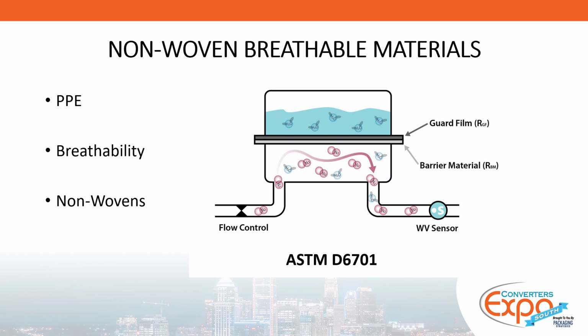And how can I be sure, conversely, that the other side is dry when so much moisture is moving into the dry environment? And this was something that had to be addressed because the need for such highly breathable, high water vapor transmission rate materials was growing. To get accurate results, an instrument method was created that is similar to an upside down cup test, where the liquid water is actually in contact with the barrier film. What that does is allow you to know that you are at 100% relative humidity, because there's no gap